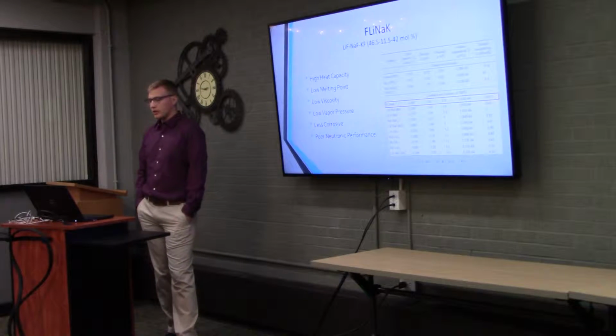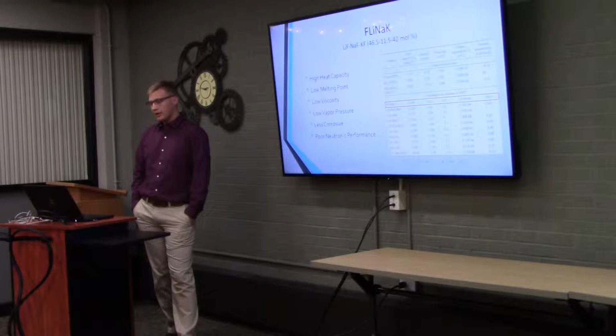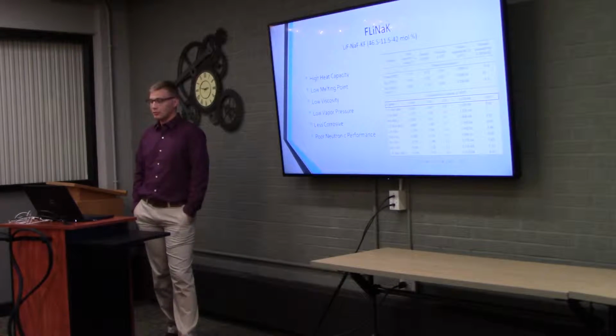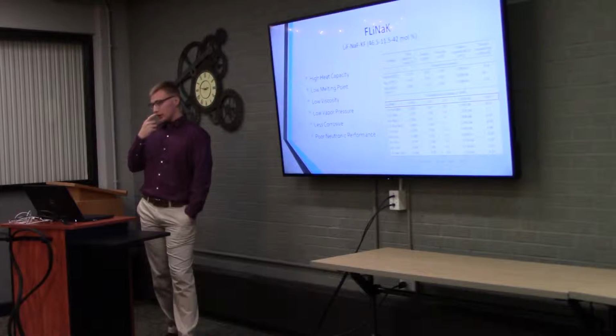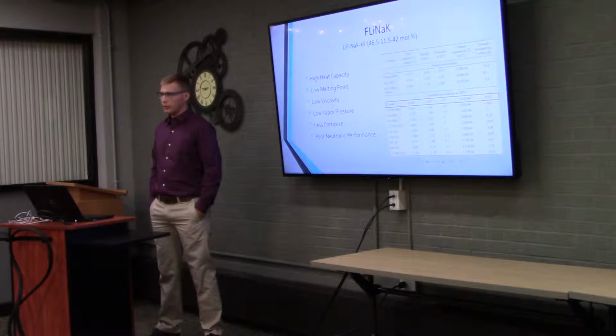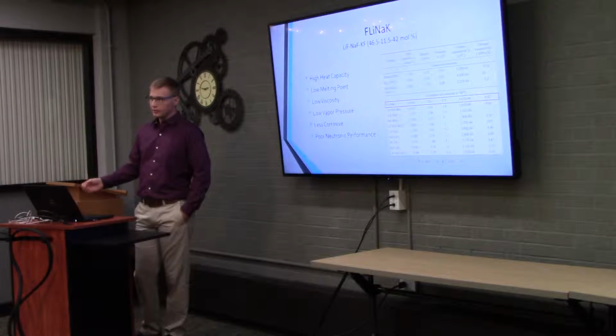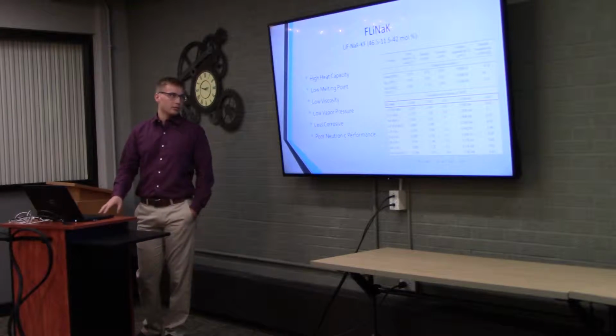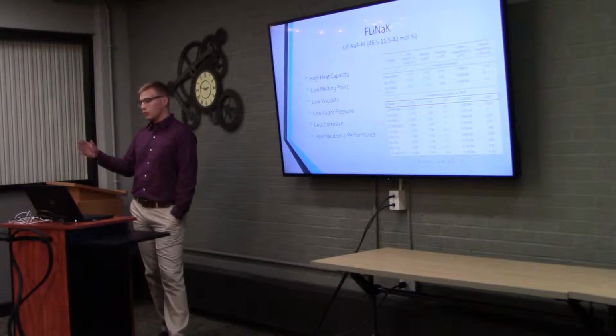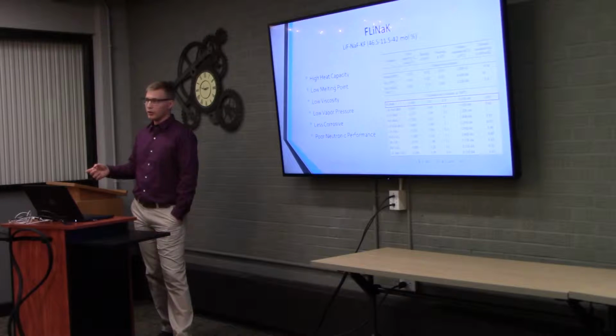And the molten salt that I chose to look into is FLiNaK. It's a mixture of lithium fluoride, sodium fluoride, and potassium fluoride. It has a higher heat capacity than a lot of other molten salts. It has a low melting point compared to other salts and a lower viscosity, which decreases the power required to pump it through the coolant loop. It has a low vapor pressure, which we talked about before, makes it safer and makes it more efficient. And it is also less corrosive than a lot of other molten salts that have been studied that could be used in the reactor. However, it has a poor neutronic performance, which means that you wouldn't really be able to use it in the reactor in the primary coolant loop. So my study is focused on the secondary coolant loop.